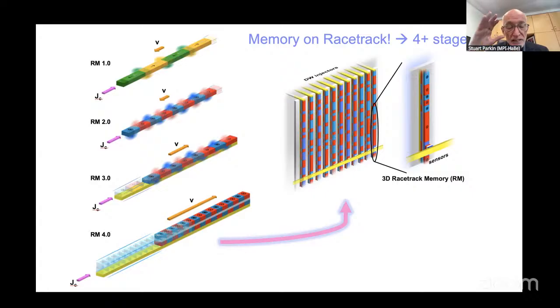And it turns out at the same time, we discovered that in this kind of racetrack, because of the magnetic coupling, the anti-ferromagnetic coupling between the upper and lower racetracks, which we introduced by a very thin anti-ferromagnetic coupling layer formed from, in our case, ruthenium, a few angstroms thick, then we discovered that these domain walls, when you pass current through this device, move several times faster than in the racetrack 3.0. So now we can make these domain walls move at speeds of more than 1 kilometer per second, making this a very, very interesting high performance technology.